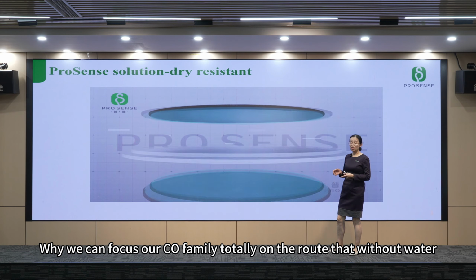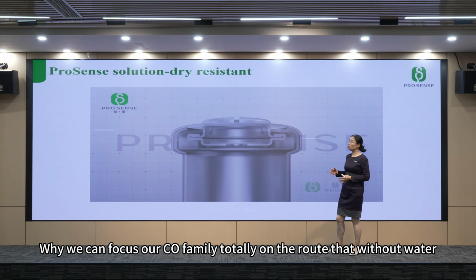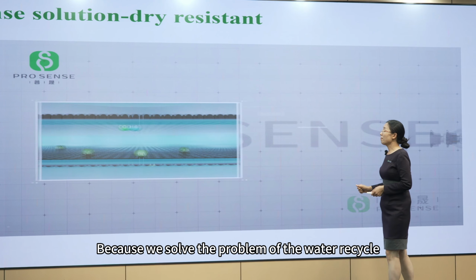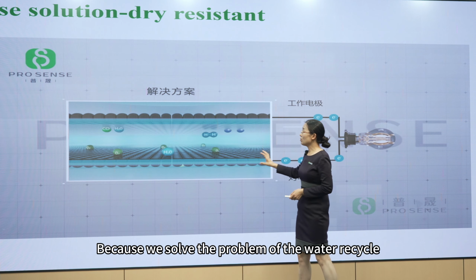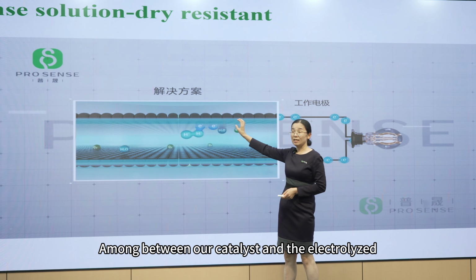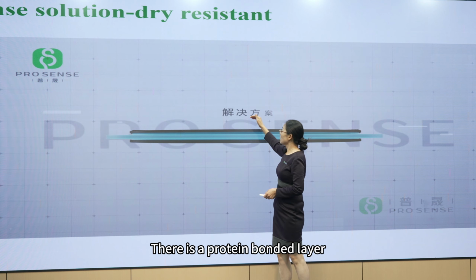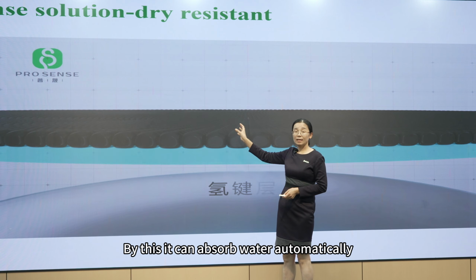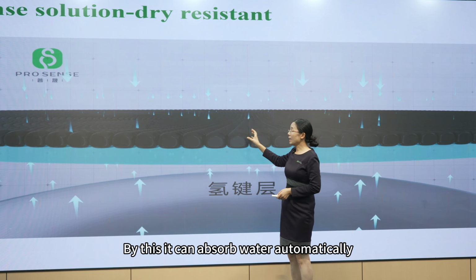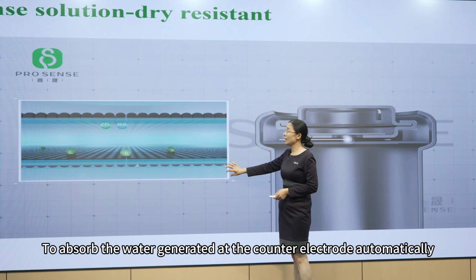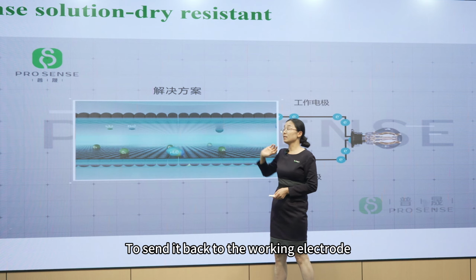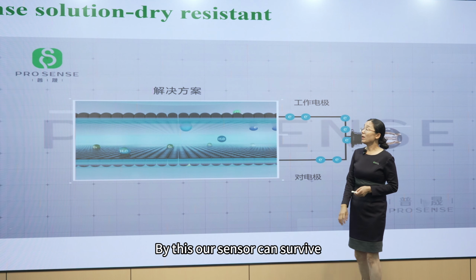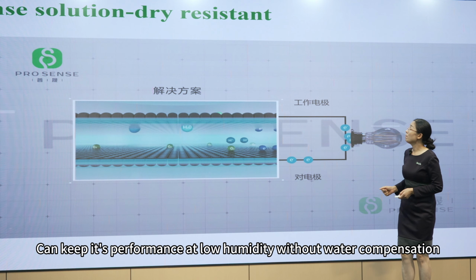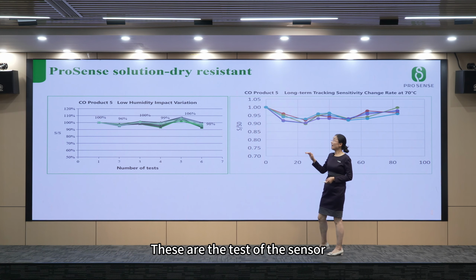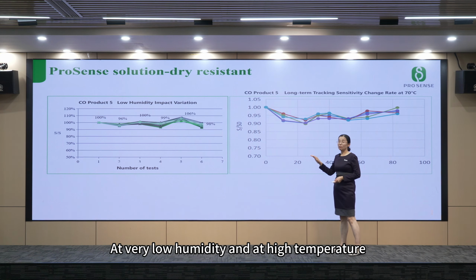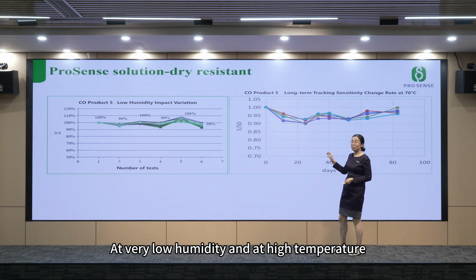Why can we focus our CO family totally on the route without water? Because we solved the problem of the water recycle. Between our catalyst and the electrolyte, there is a hydrogen-bonded layer. By this, it can automatically absorb the water generated at the counter electrode and send it back to the working electrode. By this, our sensor can keep its performance at low humidity without water compensation. These are the tests of the sensor at very low humidity and at high temperature. It's very stable.